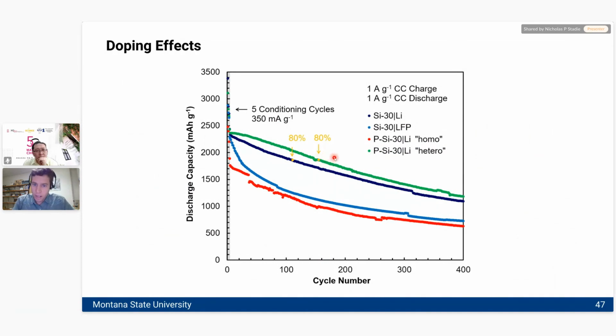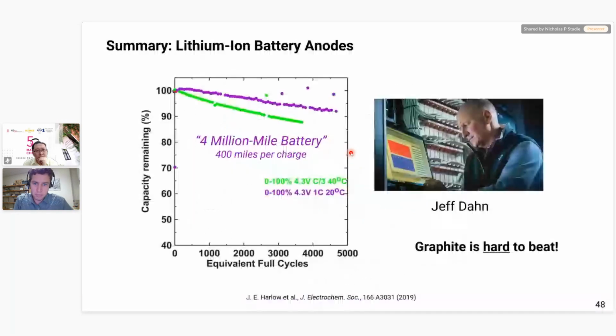That doesn't sound like a lot of cycles, but that capacity is relatively high, and it depends on what you want to get out of your battery anode. Obviously, if silicon is of interest to you, you'd probably have an application where you didn't expect to cycle it more than a few hundred times in its lifetime. So that's just something to think about. And yeah, those are among the highest results that we've ever seen reported in the literature for a liquid electrolyte pure silicon electrode.